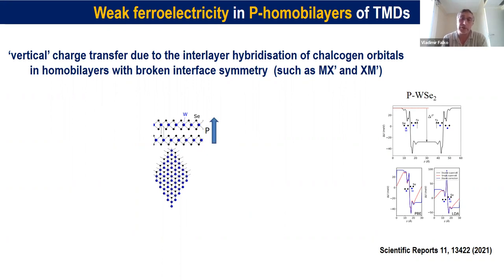Just to mention that 2H stacking is inversion symmetric because the top layer is an inverted image of the bottom layer. But for 3R orientation, this does not happen. And for a general way to put the top layer on top of the bottom layer, there is also no mirror symmetry, which in principle permits out-of-plane polarization of the bilayer, which we established by both calculating the charges